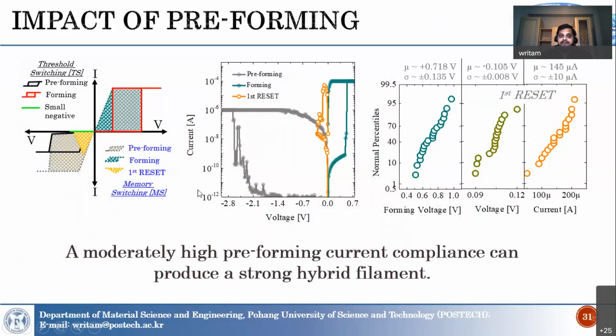Now, if you have a different kind of compliance level with the same scheme, previously for threshold switching the scheme was in the nanoampere range, but now you are in the microampere range. When you are in the microampere range, you introduce more vacancies into the channel, so your filament is much more stable, and you need a certain amount of voltage to reset the filament. This is how we can change the switching process from threshold to memory switching.